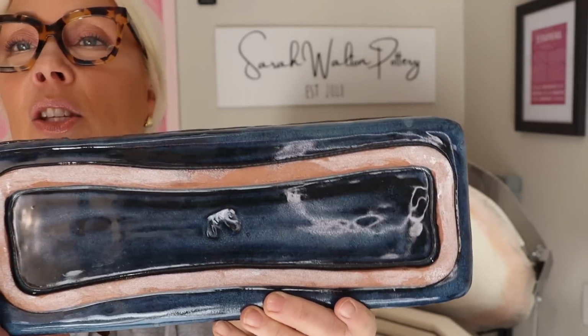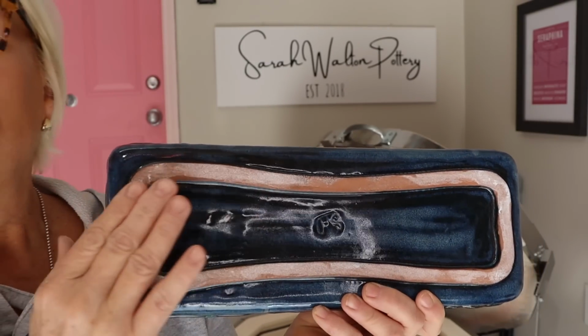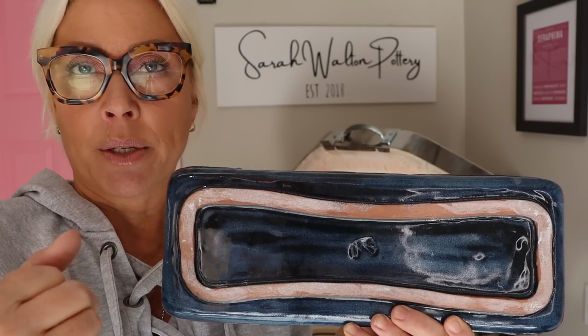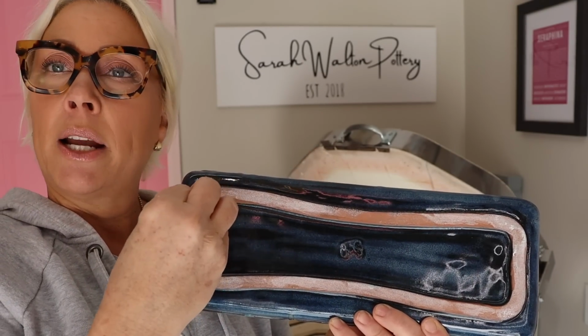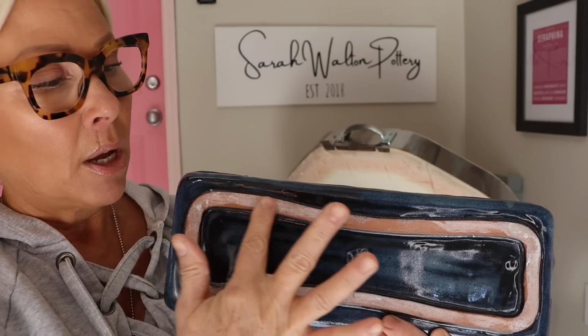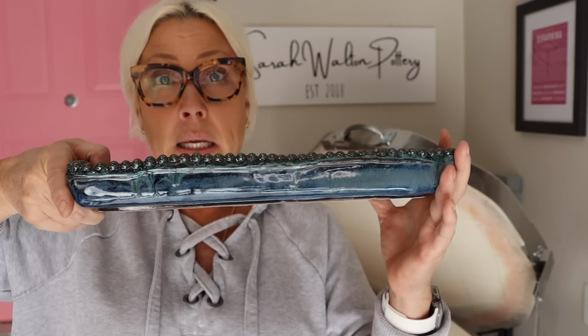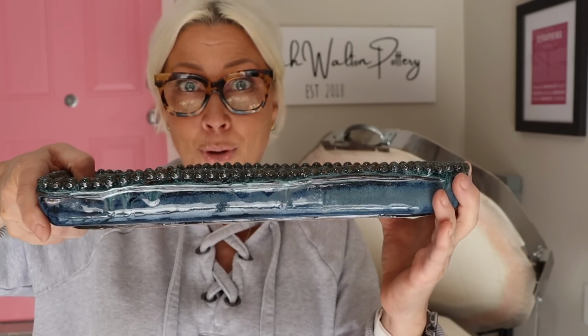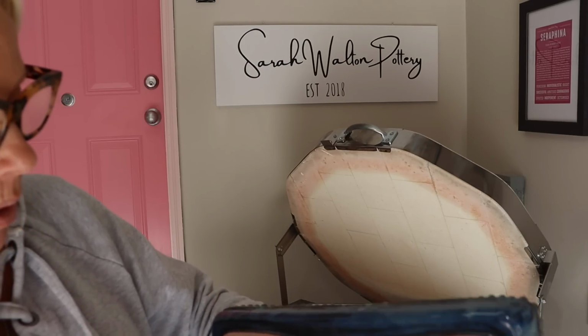I don't take any chances with large pieces. Now I will brush on the alumina hydrate, which is mixed into my wax. I don't know if I mentioned the ratio. It's a couple of tablespoons for like, I don't know, 3/4 of a cup of wax. You don't need a lot. Basically the wax just gets the alumina hydrate on. The wax melts away, leaving the alumina hydrate like little ball bearings, so that your piece can actually move in the kiln, because as it shrinks, it allows it to move and your pieces don't warp. So yes. I know I should be saving that.